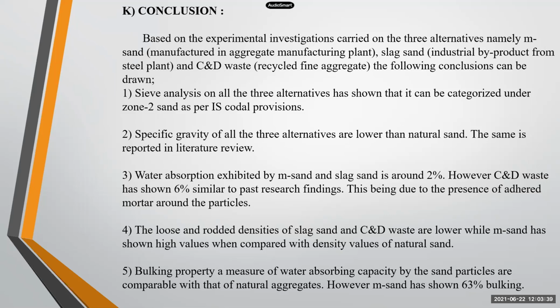Second, the specific gravity of all three alternatives is lower than natural sand. The same is reported in the literature review. Then water absorption exhibited by M sand and slag sand is around 2%. C&D waste has shown 6%, similar to past research findings, due to the presence of old mortar around the particles. The loose and rodded densities of slag sand and C&D waste are lower, while M sand has shown a high value compared with natural sand. Bulking properties, a measure of water absorbing capacity of the sand particles, are comparable with natural aggregate. However, M sand has shown 63% bulking.